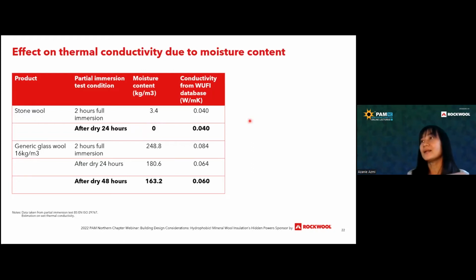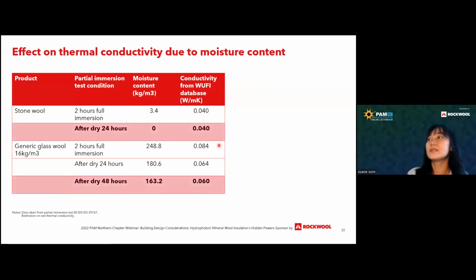And you can see that this is rounded up to, let's say, 2 digits. You can see that from that formula, 3.4 does not increase the conductivity, it's around 0.04. So when you dry, it goes back almost the same. Whereas for generic Glasswool, 2-hour full immersions, the moisture content is very, very high, around 250, and your conductivity will increase to around 0.08, which is still quite high. And let's say here, after dry 24 hours, 180 moisture content, you get 0.06. And even after 48 hours, your moisture content is 163, and you will get around